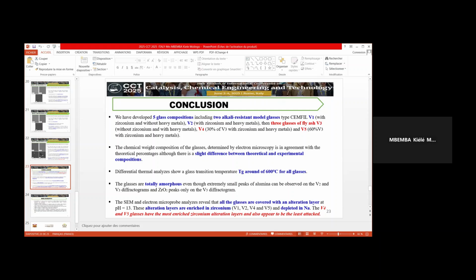The SEM and electron microprobe analysis reveal that all the glasses are covered with an alteration layer at pH 13. These alteration layers are enriched in zirconium for V1, V2, V4, and V5 glasses, and depleted in sodium. What we have to retain from this study is that V4 and V5 glasses have the most zirconium-enriched alteration layers, and also appear to be the least attacked in alkaline solution.